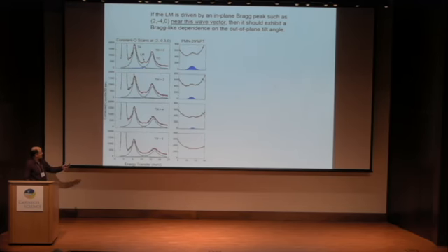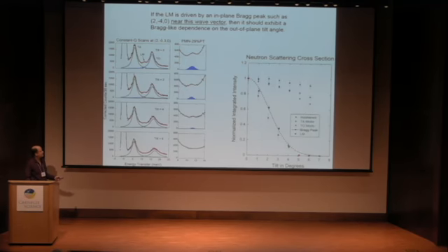So we took a series of data at a slightly different Q. This is 0.3, and we did tilt from 0 to 6. We see that this local mode dies. Now, Mike did provide an alternative explanation for that based on coupling of the PNR mode and the optic mode and so forth. But I think this is a far simpler explanation. And in fact, it's rather dramatic. This local mode dies exactly like the Bragg peak. It's not similar. It's essentially identical. Whereas these other modes, especially like the incoherent scattering or the acoustic mode, are all very, very slow and soft functions of tilt, which is what you'd expect a phonon mode to be like.